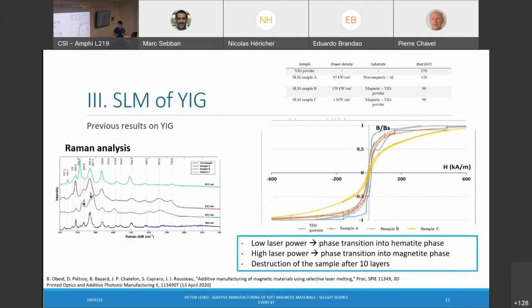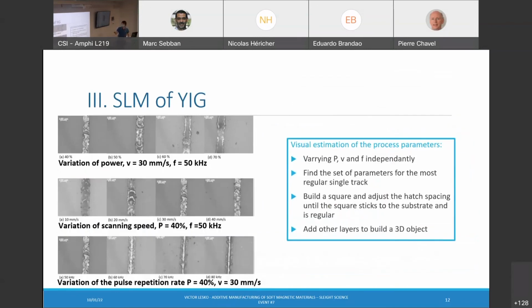These are the previous results which have been published on YIG. Many parameters have been tested, and the Raman analysis shows that for low laser power, there is the occurrence of a hematite phase in the sample, and for higher laser power, there is a phase transition into a magnetite phase. It was also reported that the sample was destroyed after 10 layers because of residual stresses. The other figure shows that the sample is still magnetic after the SLM process. And this is to show that we try to find the best parameters for the SLM, and we vary the power, the speed, and the frequency.